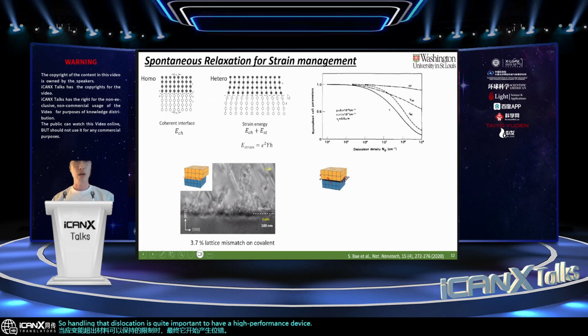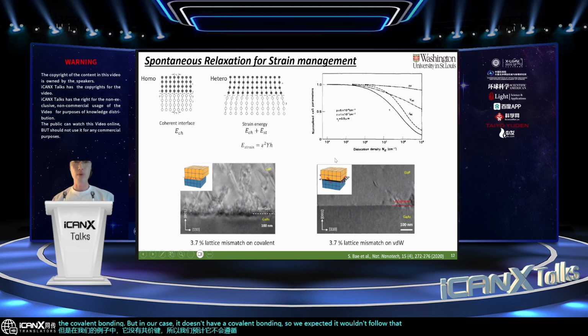But in our case, it doesn't follow this situation. That is mainly because the original dislocation comes from the strain energy, and strain energy comes from the covalent bonding. But in our case, there is no covalent bonding, so we expected it wouldn't follow that scenario. What we found is that another scenario exists, which we call the interface sliding situation. Interface sliding has a much lower threshold energy compared to the threshold energy for dislocation introduction, so that eventually we achieve an 8 times smaller defect density in our system.